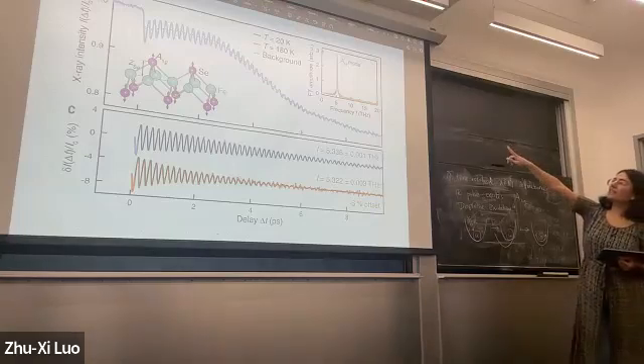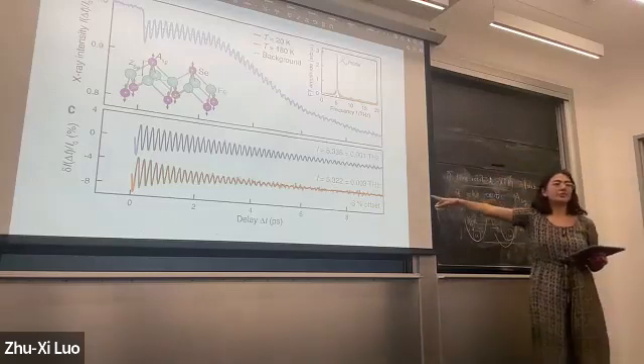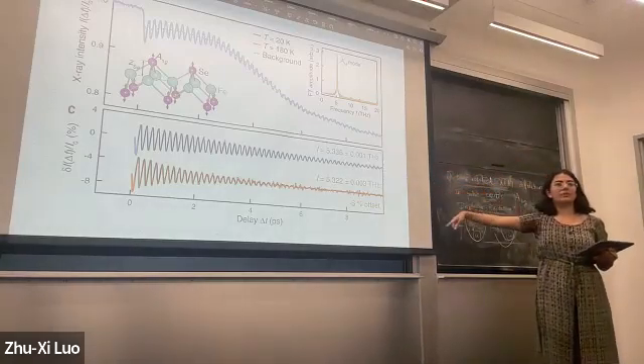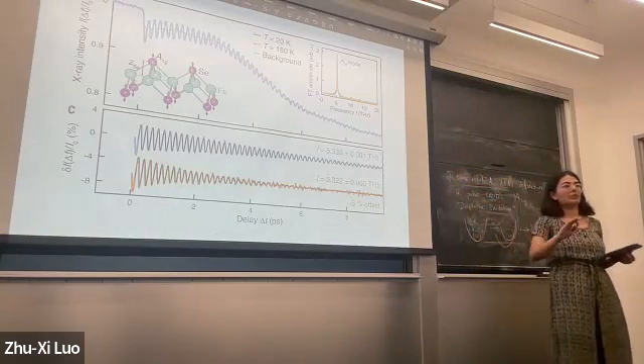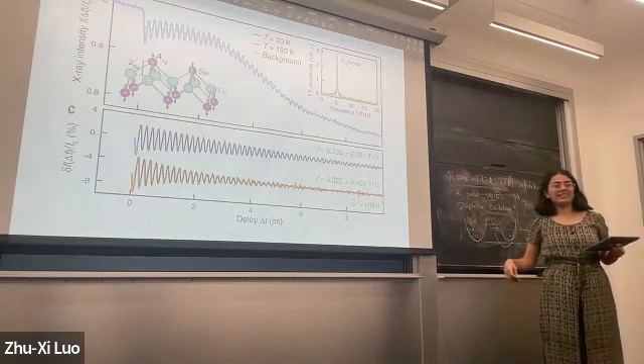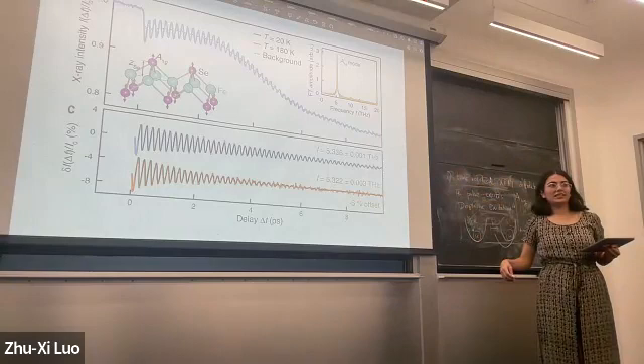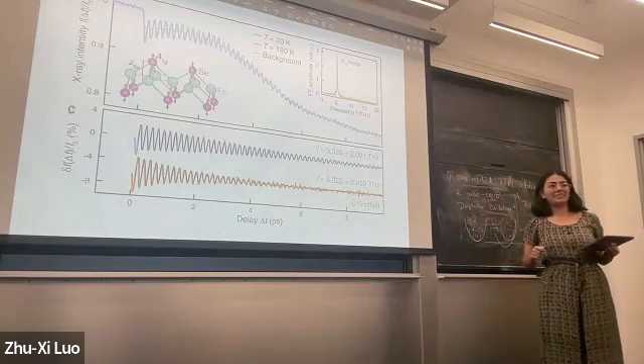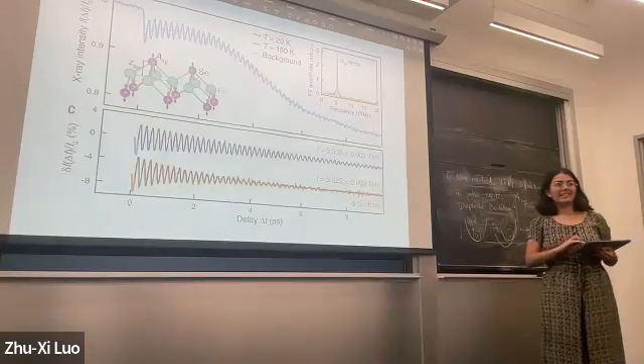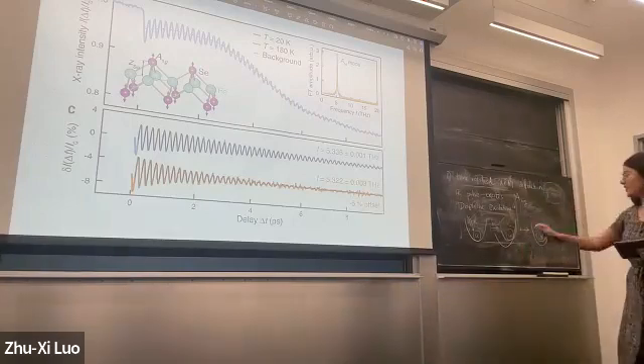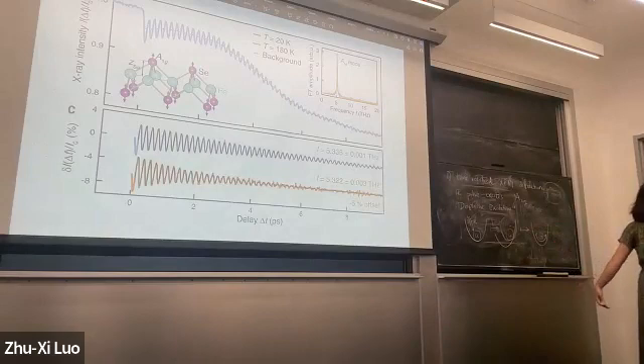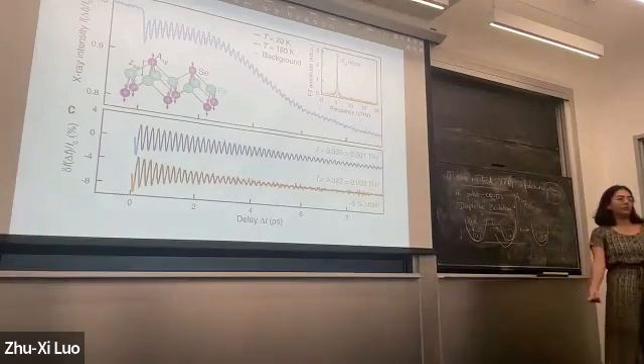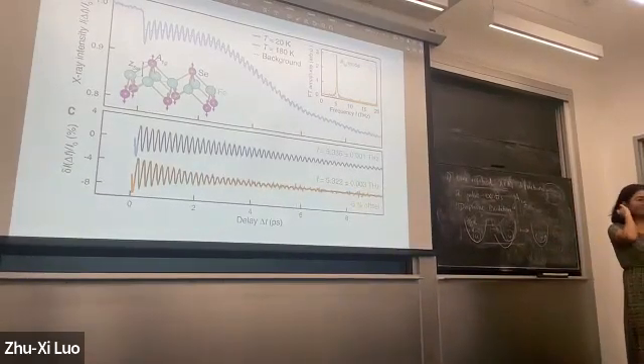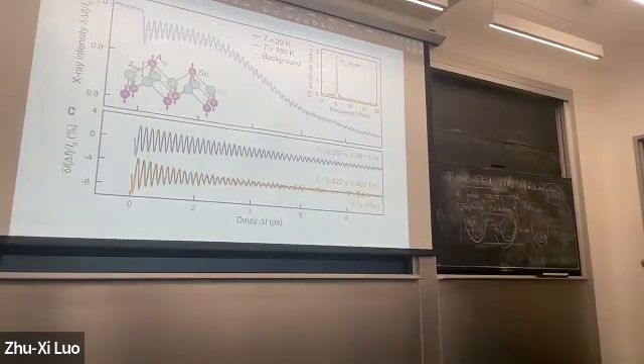Well, okay, wait, so this peak is just from Fourier transforming the data. So it's not like optical absorption data. The frequency of this oscillation is not necessarily the frequency of the photon. The frequency of the phonon is different from the frequency of the IR. Yes, because I think there's this sort of intermediate step going on, which means the light is not coupling directly to the phonon. It's coupling to the electrons, which then have impact on the lattice structure, which gives me the phonon. So you need an extra term for conservation of energy or something like this. Yes, there is.